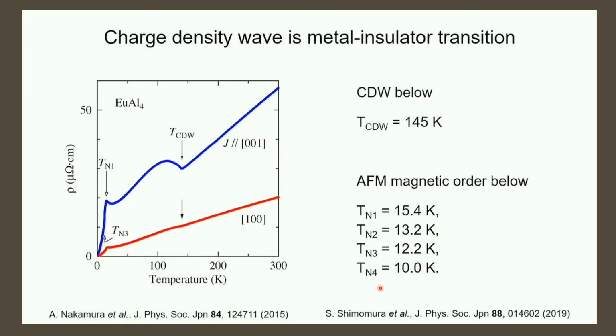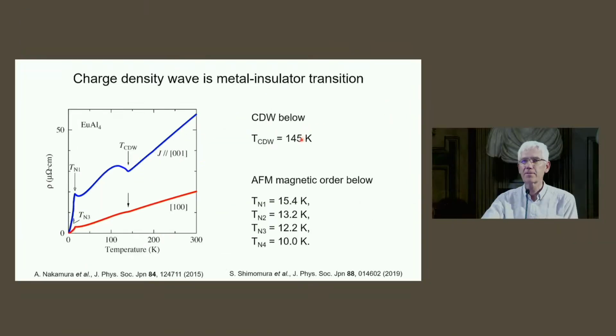Shimomura found 4 successive magnetic transitions to different types of anti-ferromagnetic order. The charge-density wave transition is at 145 Kelvin, so much higher. But one can imagine the symmetry, which we arrive at below 145, is the starting point for the symmetry of the magnetic phases, so quite important.